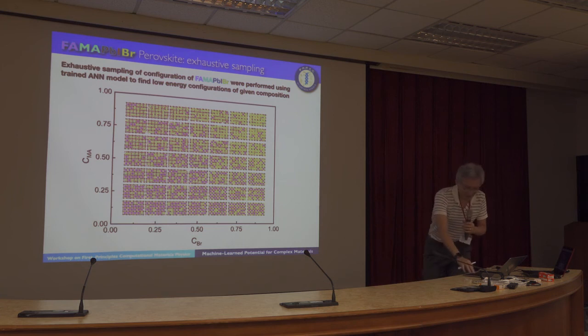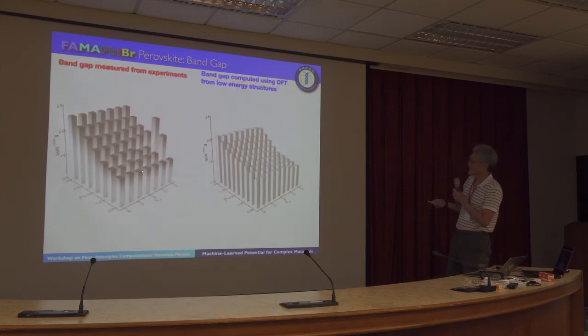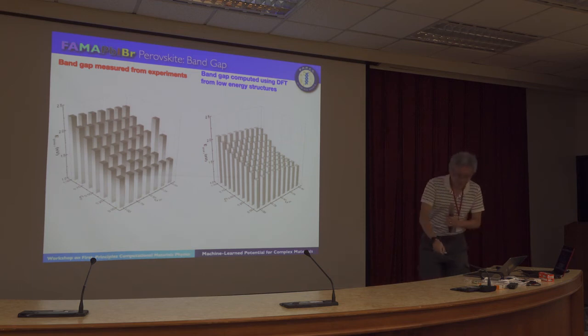But before this, we need to first do some small validation. So this is the band gap we compute from DFT. But I have to stress that because there are 1,700 atoms in our system, we only take gamma points. We just take a single point. There's no relaxation. We just directly use the lowest energy structure from the neural network potential calculations, and just do gamma points. And of course, you can see an underestimate here. But you see the trend is fine. And I guess these 2 points, there must be something wrong with the experiment.